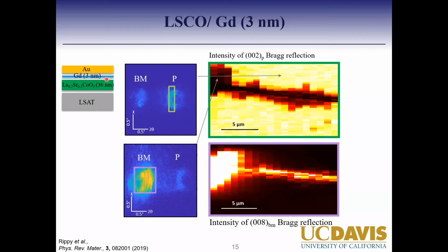My second quick question is, if you have questions about the dependence along the z-axis, is it possible to go below the total external reflection angle for your film to do something like a reflectometry experiment? You maybe don't even have to do a nanodiffraction experiment. And if there's a Bragg peak that you can access at those small angles, you might be able to distinguish if you have these two phases at the surface.